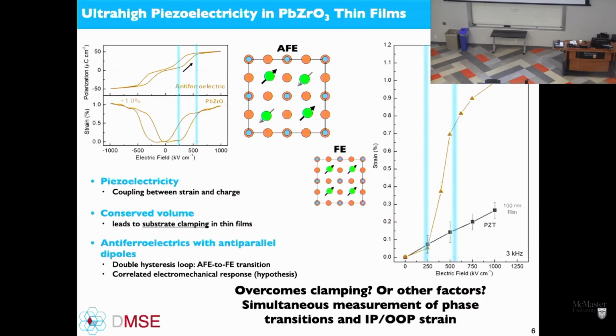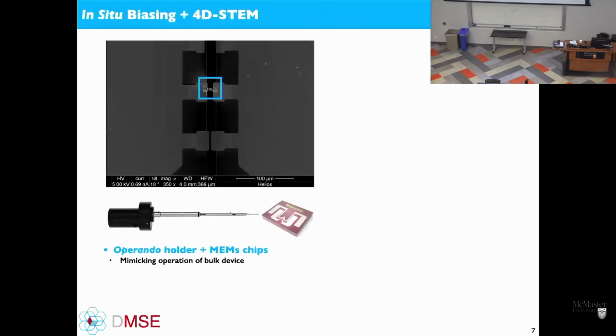And so what we ultimately need is information about what phases are present and the in-plane and out-of-plane strain as a function of bias. And these are very tricky experiments to do when the film is growing on a substrate. You can go to a synchrotron to try and do this, but you need a synchrotron, and I don't have a synchrotron in my backyard.